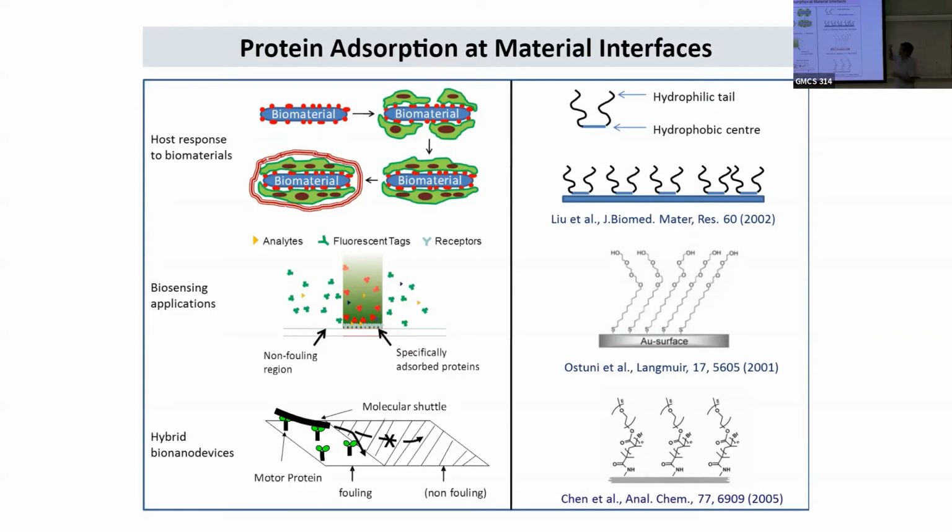There are many different ways you can get them to stay on the surface, either just through physical adsorption, or you can cross-link them. For example, if you have a gold surface, you take your hydrophilic polymer and attach a sulfur group to it, which then forms a bond with the gold surface and will stick covalently. So it'll be really hard to take it off.